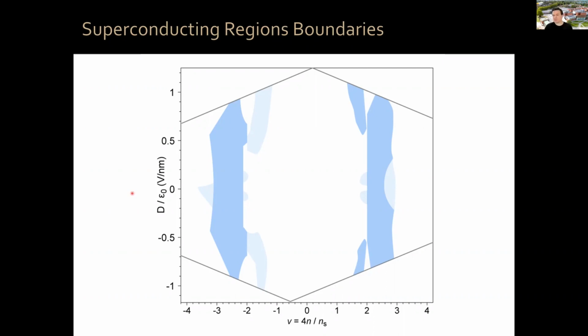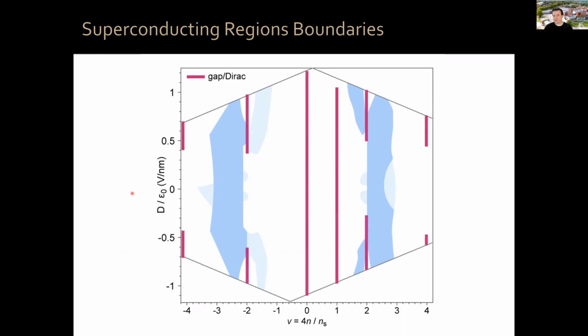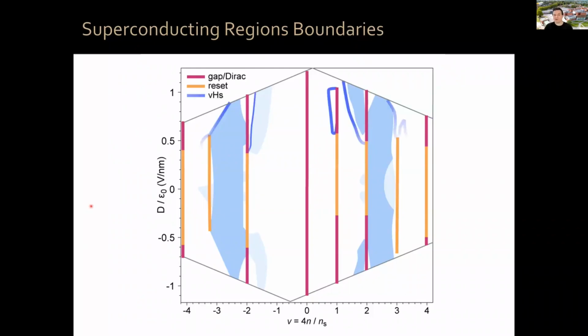Now let me put the features associated with each of those three situations in the normalized Hall density in this map. Gap or Dirac behavior is seen along these red lines. The most pronounced one is charge neutrality, but also other regions show gap or Dirac-like behavior. Resets occur in these regions, so basically at almost every integer at zero displacement field. And Van Hove singularity behavior occurs in those regions.